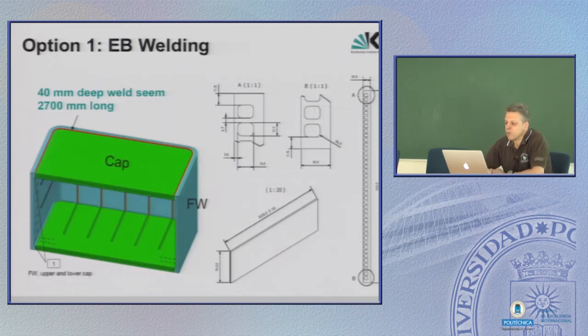The problem here is not to fabricate the caps. This could be done similar to the first one, but you have to perform a weld along this line. The weld line is 3 meters long, which is not a problem. Also the bend is not a problem, but the thickness of this cap is about 40 millimeters. So you have to perform a 40 millimeter deep weld, and in the vicinity of the weld there are already the cooling channels. So the weld has to be quite narrow, deep, and long. And this is the difficulty with such a weld.